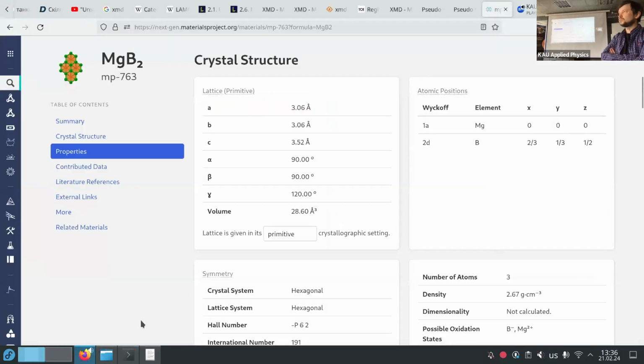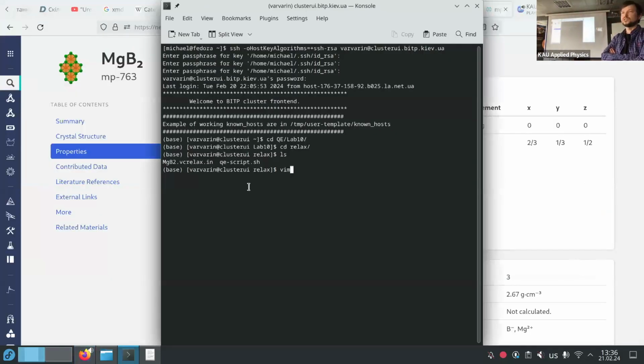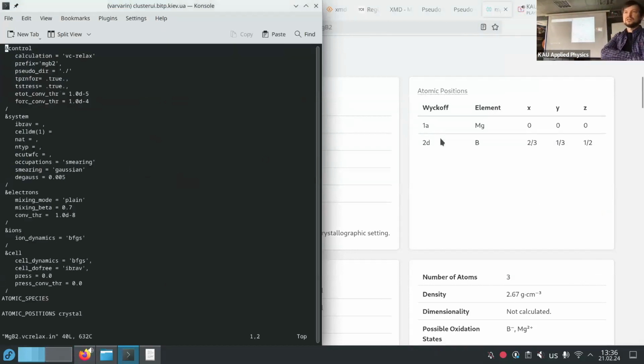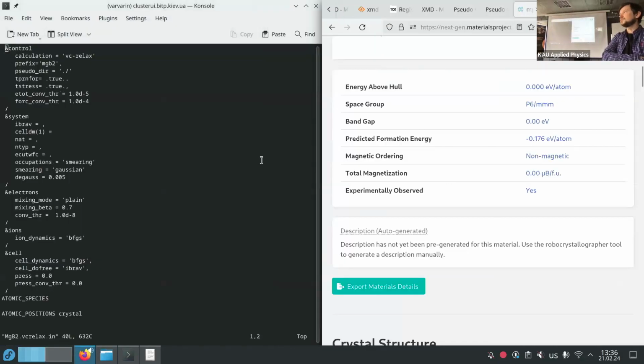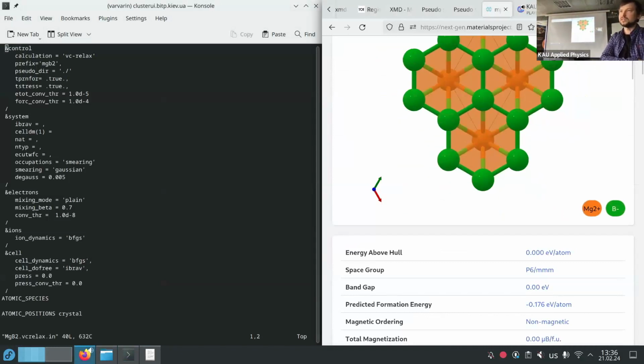If you want to see some tiny effects, for example, if you use spin orbital coupling in addition to full relativistic, you can see that some bands slightly split. It means the effect of spin orbital coupling. You should spend a lot of computational time to get this, and in most cases, it's not so different. It's not so important. Maybe it's important when you make really deep research, but in most cases, when you should get some band structure, the common band structure will be okay.